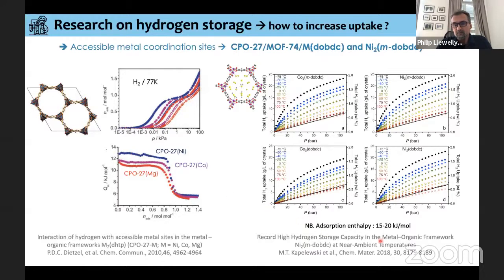More recently, the group of Jeff Long has looked at a very similar material to this one, again with different metal centers, and they showed that the adsorption enthalpy was even higher. They suggest between 15 and 20 kilojoules per mole, so slightly higher than these ones. So this may be a way forward in making materials for hydrogen storage.